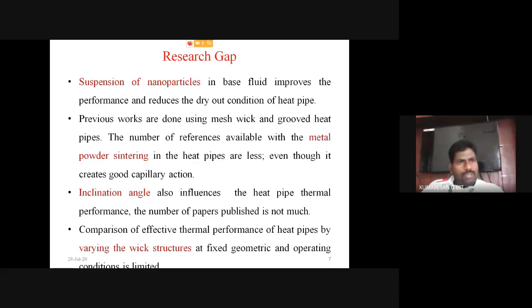So we know that porosity and permeability have an inverse proportionality. So it is very difficult to attain both porosity and permeability in a single wick structure. But wick structures made with metal powder sintering have very good porosity and permeability. But the number of works available with sintered wicks is very small.